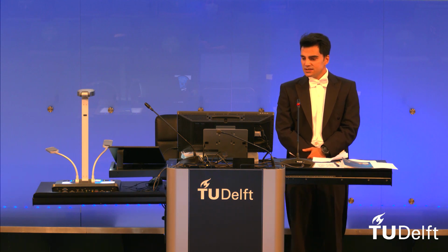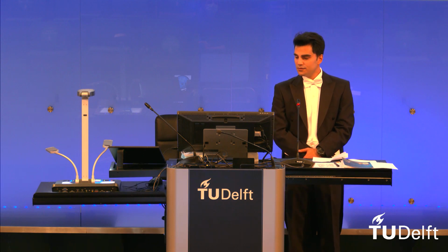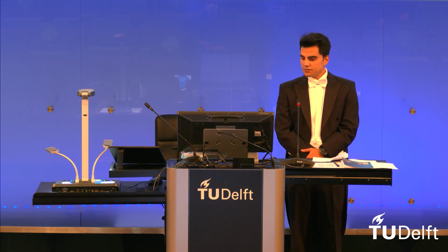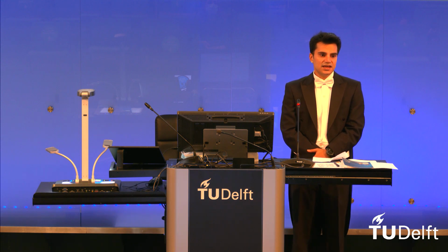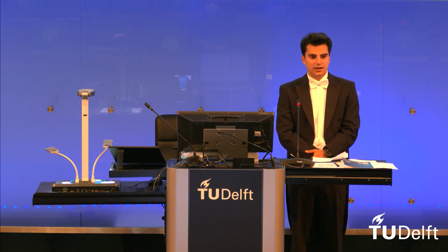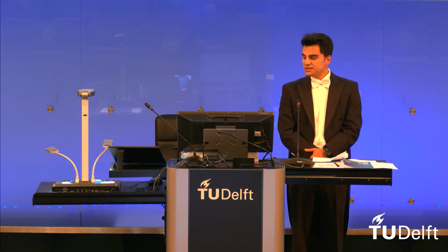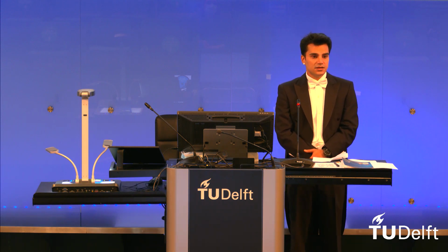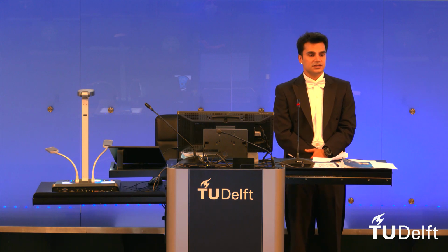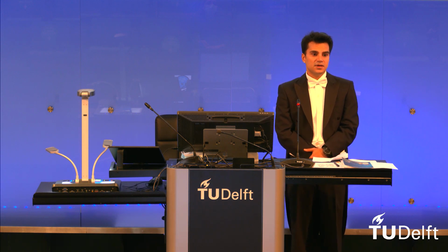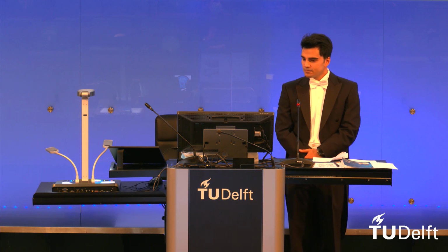In some critical cases, we saw that the temperature could exceed the temperature which is needed for austenite to form on the rail surface. We call it the white etching layer formation. The term white etching layer has been used for a layer which has a martensitic nature, and it is very prone to fatigue initiation. Of course, there are many researches ongoing on this topic, and people in the literature believe that white etching layer is quite associated with the squat defects.